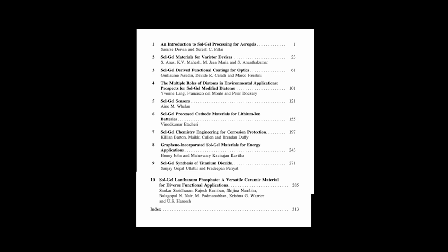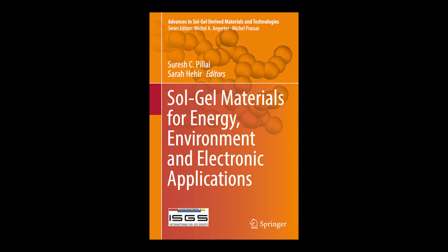And in solar cells, particularly the well-established dye-sensitized solar cells, DSSCs, TiO2 is the traditional semiconductor workhorse. How does adding graphene via sol-gel supercharge its performance? Graphene plays a couple of key roles here. It doesn't just sit there passively. It provides an almost instantaneous electron transport pathway out of the TiO2. When researchers incorporate graphene into TiO2 photoanodes, sometimes using composites like N-doped TiO2 graphene prepared via sol-gel methods, they consistently see significant increases in the solar cell efficiency. The chapter cites up to 9.3% efficiency reported in some cases.